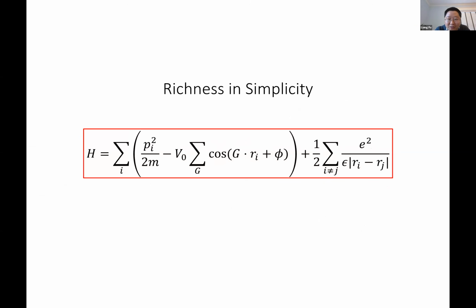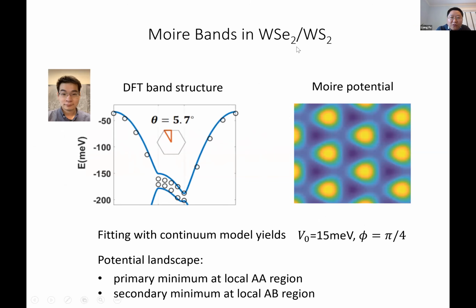Yeah. Okay. So this is what I'm going to focus on. I'm going to focus on the physics contained in this universal Hamiltonian for the TMD Moiré superlattice. So the first thing we look at is the electronic structure, the single particle non-interacting band structure, more carefully for this material WS2. Using a DFT calculation for a twist angle of about 6 degrees with more than 600 atoms per unit cell, we can obtain the DFT band structure showing these dots here, and fitting this DFT band structure with this continuum model with the cosine potential will tell us the potential strength and this Moiré potential parameter phi.